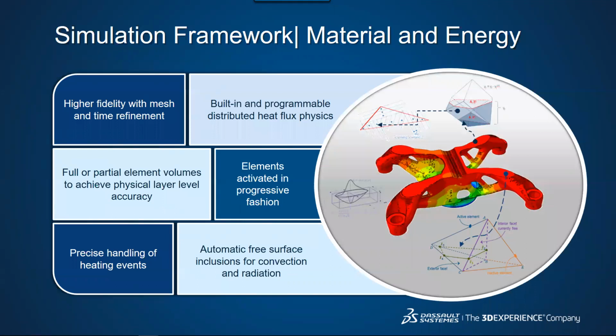So during the simulation, any given element can be either completely or partially filled with material, or empty. And the solver is keeping track of this evolution of material as the build is occurring. It's monitoring the mass, inventory, and distribution, and accounting for this addition of material during the printing. Finally, we also have partial facet areas that are computed, and this allows us to have a precise assessment of cooling on the free surfaces of the part, regardless of the coarseness or fineness of your finite element discretization. So we have radiation and convection modeled on the free surface of the part as the build is occurring, and the solver is keeping track of all of that for you.